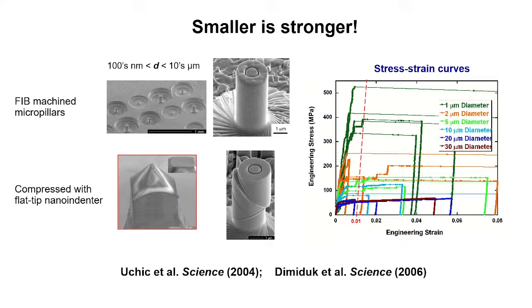So you can see that you get very nice, initially single slip. It depends on what the orientation of the pillar is. And then they plotted this as a function of pillar diameter from 1 micron to 30 micron diameter. And what you find is when you get to about 30 micron pillar diameter, you get flow stress that behaves like this. And this is very similar to what the bulk flow stress of nickel is. Right? So if you took a bulk sample that was millimeters in size and you plotted the engineering stress strain curve, that would look like this. But then when you go to 1 micron diameter, then the strength increases dramatically. So the smaller pillars were dramatically stronger than the bigger pillars.